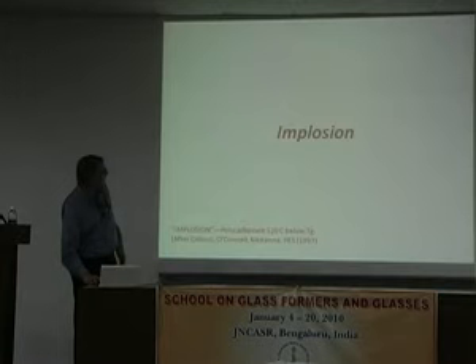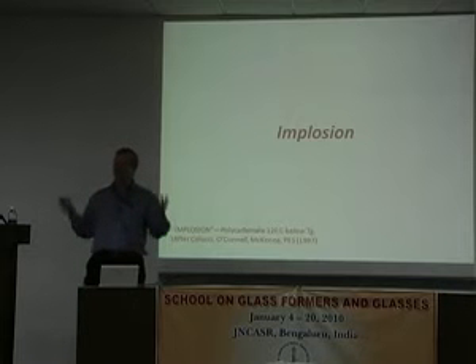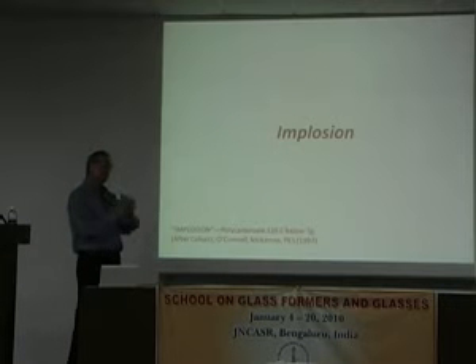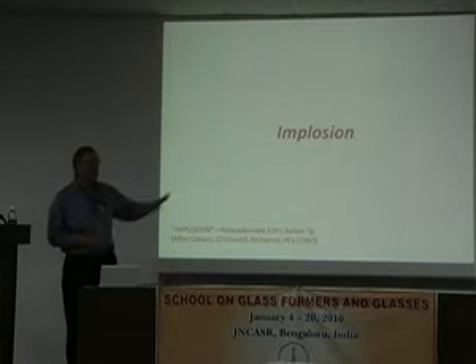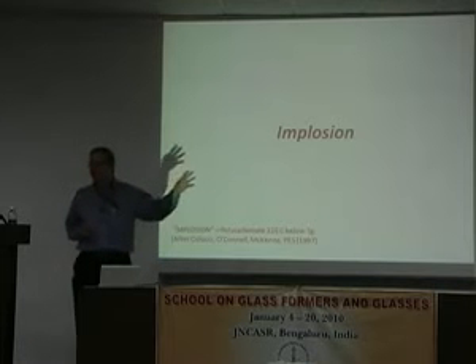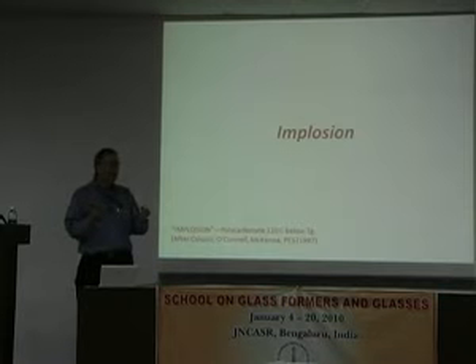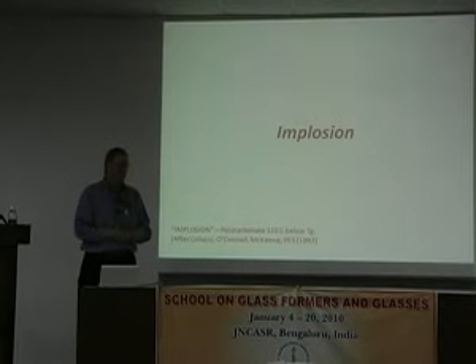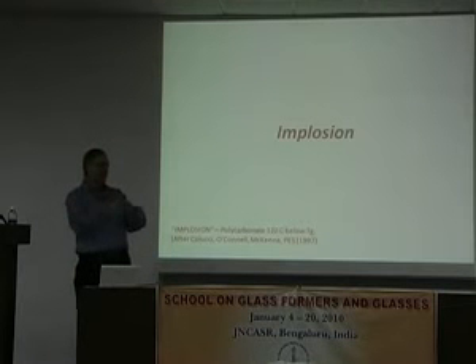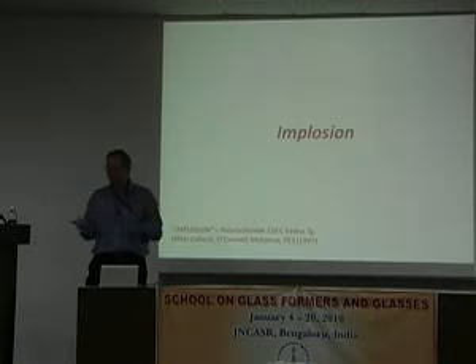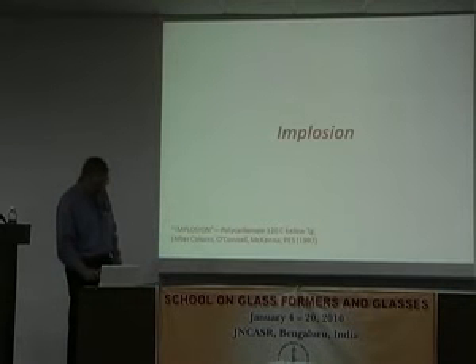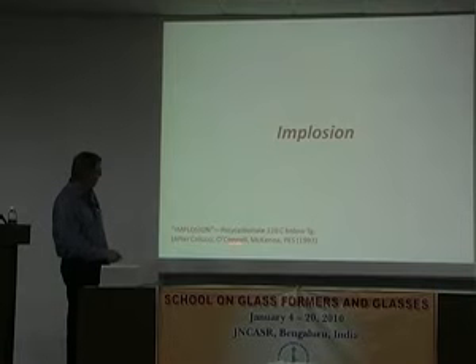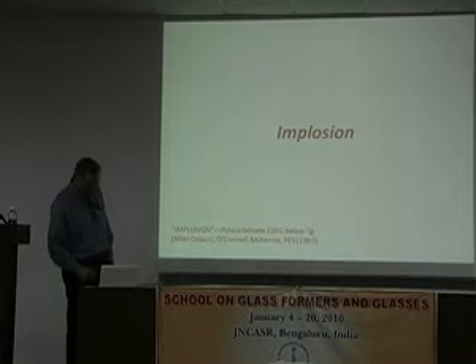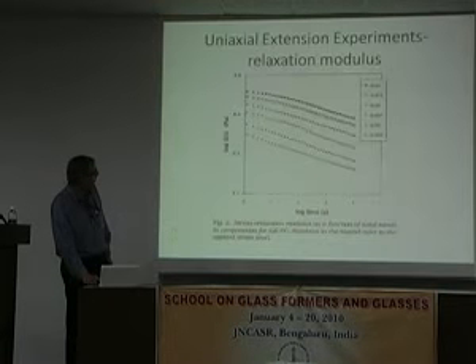Okay, and the last thing on this mechanical part is this implosion event to show how complicated these interactions are. Now I'm going to take a material far below the glass transition. Generally, I've been working near the glass transition so I can get into equilibrium sometimes, because that's where we're interested. We're interested in complicated thermal histories and getting memory effects and so on. But this is a polycarbonate 120 degrees below the glass transition temperature.